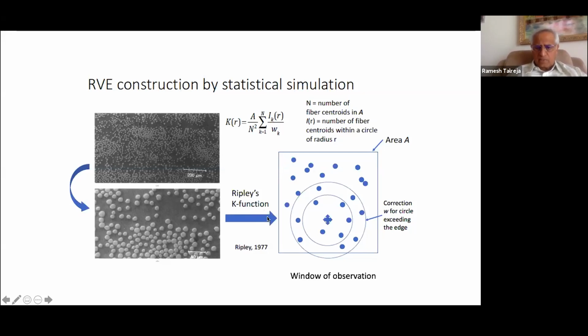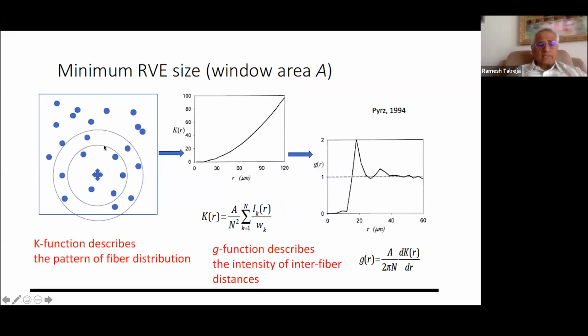But essentially, what is to be done is to take a certain representative area A, field of view, in which you go to the non-uniform distribution of fibers and construct this K function. So let me show what that is. So here's that picture again, and so you go to any arbitrary fiber, draw circles of radius r, and plot that radius r value here, and the K function then does a statistic of the neighborhood of that particular fiber. That is, where are the other fibers related to this one here? So what that does is to produce a K-r curve that is characteristic of a certain pattern. So it's like a pattern recognition idea.